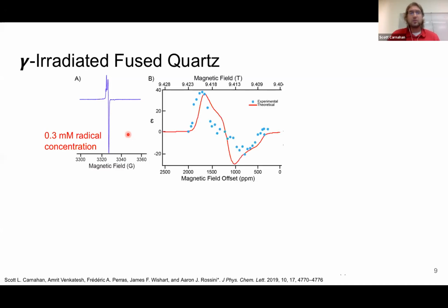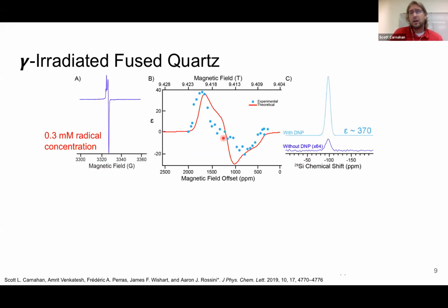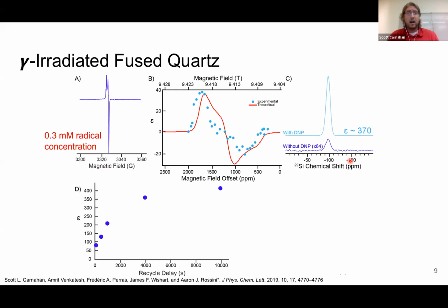When we do a field sweep, we're able to fit it to a solid effect profile. So with a low radical concentration and the splittings between the positive and negative maxima, we're pretty confident that the DNP is happening through the solid effect. When we do NMR, we're getting these large enhancements, up over 400. If we use longer delays, you can see a 10,000 second delay is about 3 hours. So we're waiting 3 hours to get one scan.